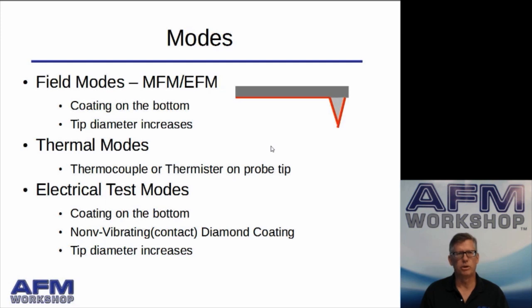Many people like to do modes with their atomic force microscopes. For example, field modes, which include MFM and EFM. In these types of measurements, there's a coating put on the bottom of the cantilever, and the coating could be some magnetic coating or some conductive coating. But what's important to remember is that when you put that coating on with vapor deposition, the diameter of the probe increases.